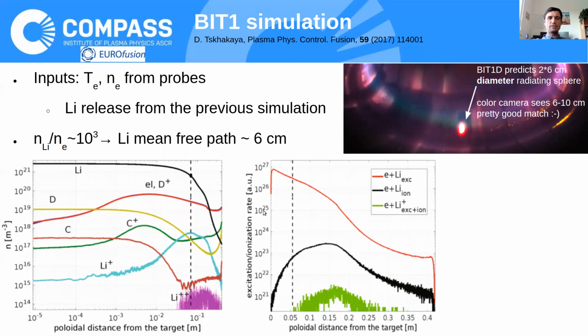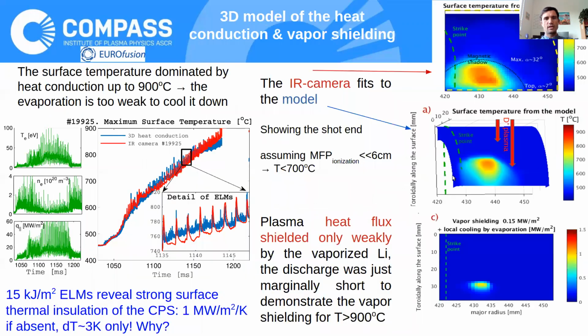Here you can see the excitation and ionization rate. At about 6 centimeters from the target, the intensity of radiation of the ionized lithium should decrease by a factor of 3, and down by an order of magnitude at 10 centimeters away. And this is pretty close to what we measured with a visible camera, that there was a radiating sphere of 12 centimeters diameter. So it's a pretty good match, taking into account that we have a lot of unknowns in the code.